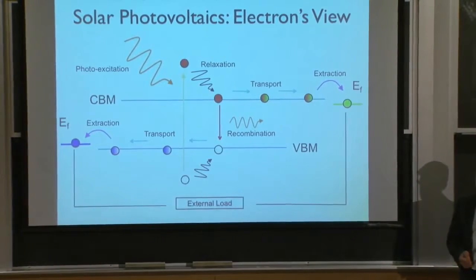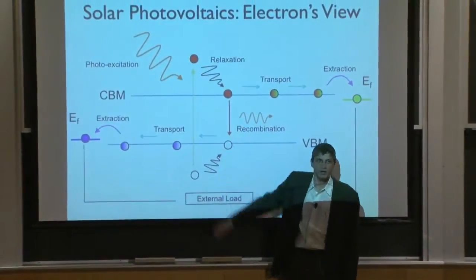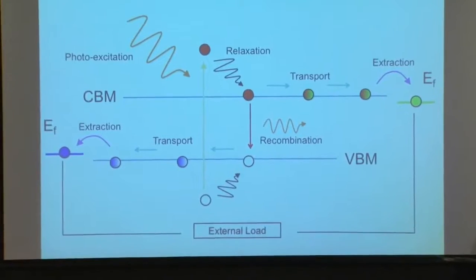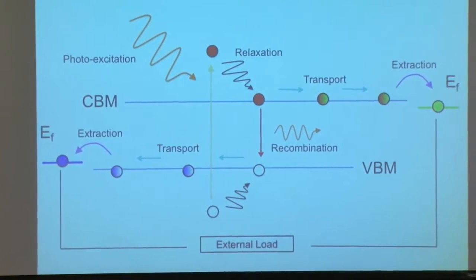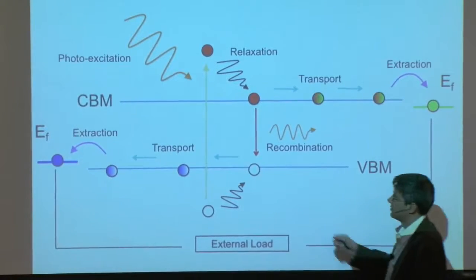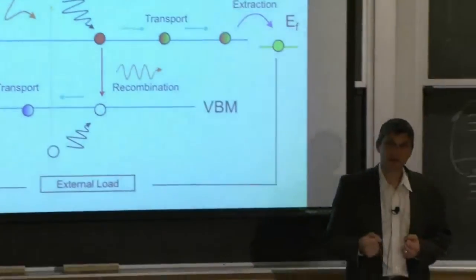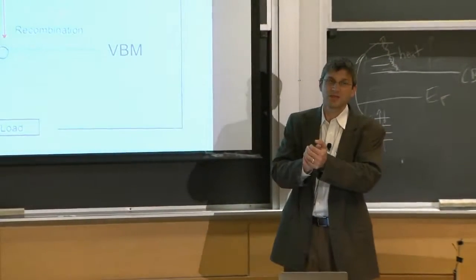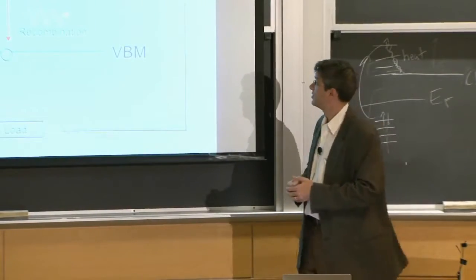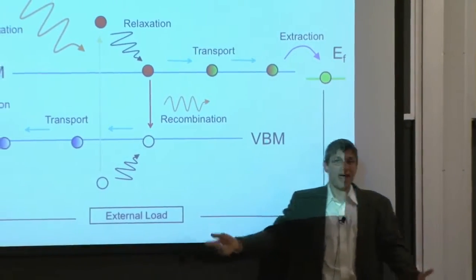But in a plastic solar cell or an organic solar cell, these are really strongly bound. They really want to be best friends. They're a half an electron volt bound instead of milli-electron volts. Those are strongly bound excitons. So a p-n junction won't do it. You can't do that because they're going to be together unless you rip them apart. And if you don't rip them apart soon, they're just going to collapse and you're going to lose all the photon's energy. The electron and hole will recombine, and they'll emit a photon. That's a bad thing.